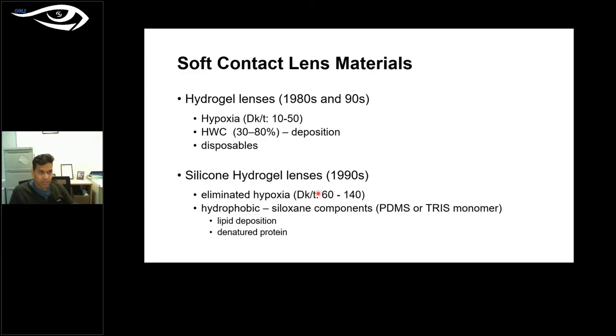One major problem with silicone hydrogel lenses was that the material consists of siloxane components. PDMS, polydimethyl siloxane, and tris monomer generally are the core components of silicone hydrogel lenses. And these siloxane components make the lens surface hydrophobic. Hydrophobic means it's not water loving, it's a water hating surface. We want lenses which are water loving, because when you place it on the eye surface, we have tears on the eye, and we want the tears to easily spread on the contact lens surface. But unfortunately, these materials are hydrophobic and therefore tend to attract deposition. Of course, there was deposition with hydrogel lenses also, but silicone hydrogel lenses particularly get lipid kind of deposition, and also denatured protein deposition.